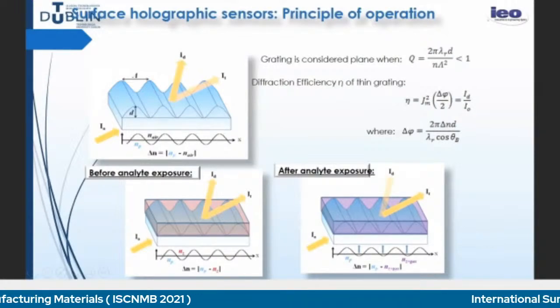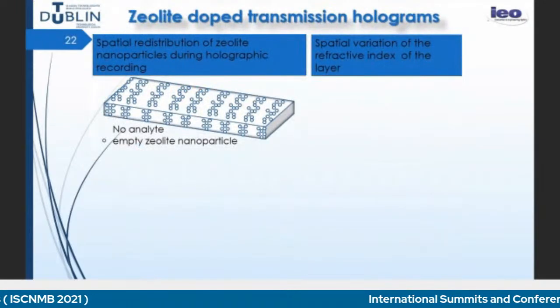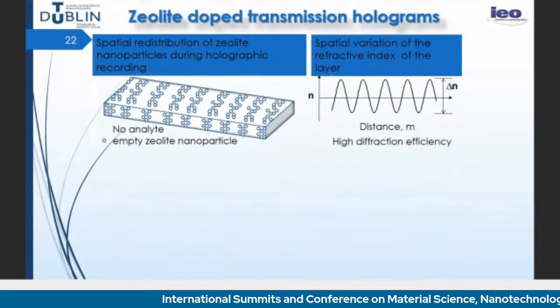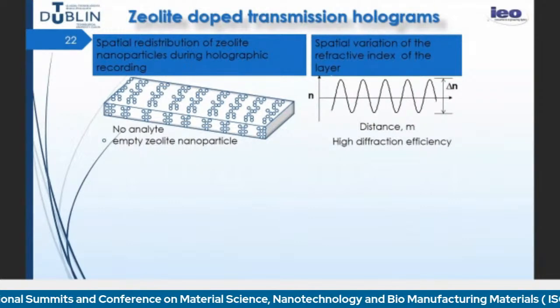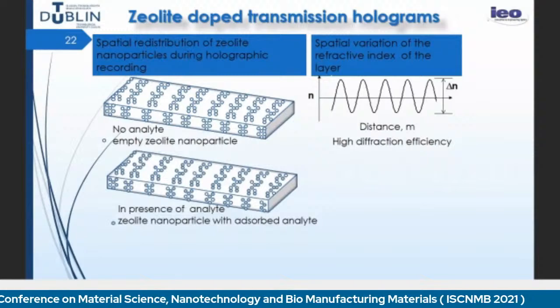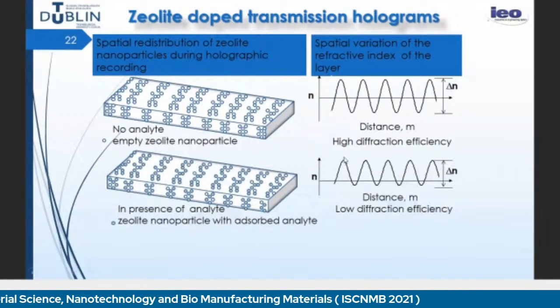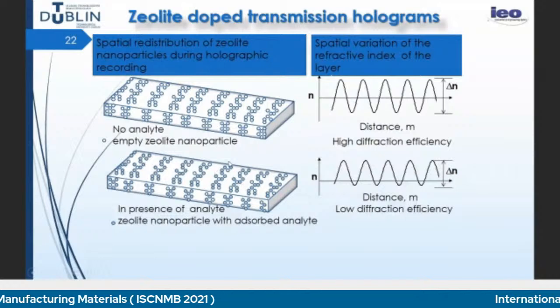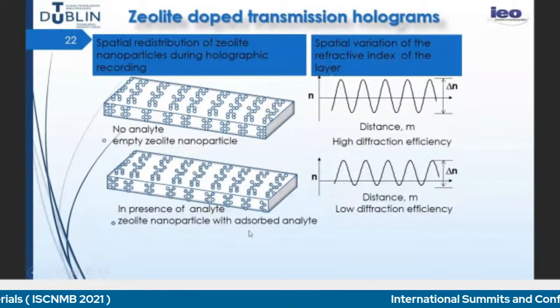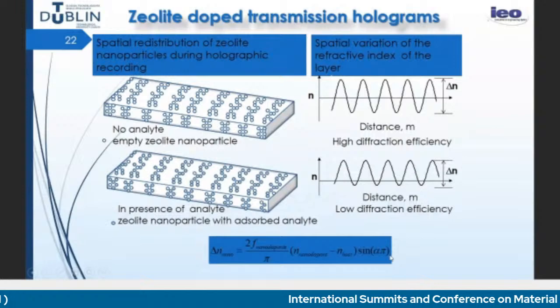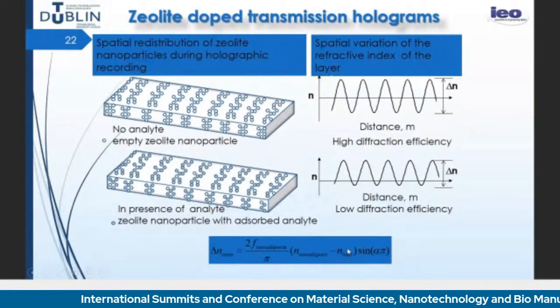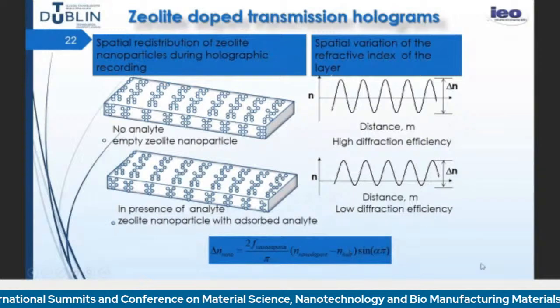How does zeolite work? If we have the zeolites redistributed or coated on the surface of the layer, we get some refractive index modulation in the layer. When they absorb the analyte, this refractive index modulation changes, due to the fact that the refractive index in the areas where the zeolite is also changes. And this change depends on the volume fraction of the redistributed nanoparticles, and the difference in the refractive index of the nanoparticles and the host.